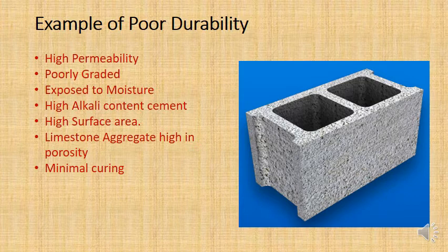It also has quite a high alkali content, a very high silica content in the limestone. So with the high alkali content, with the cheaper cement they're using, there can be alkali silica reactions. High surface area, that's related to the high permeability. And finally, they often don't cure them for very long. They might cure them for maybe a day or two, and often all they're doing is sprinkling it with water. So even in that 2-3 days of curing, it's often drying in that time anyway. So very poor quality management.